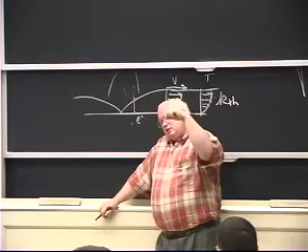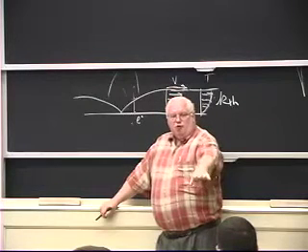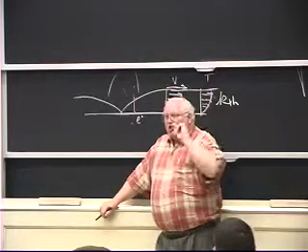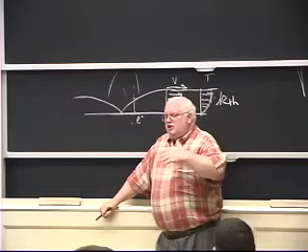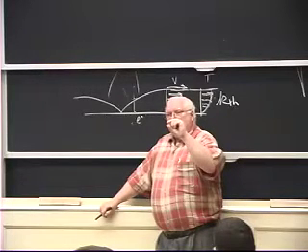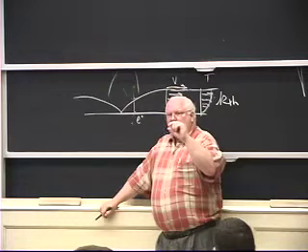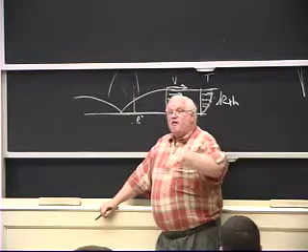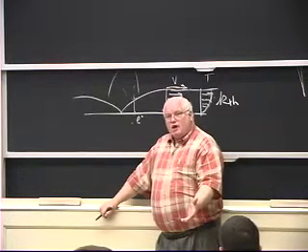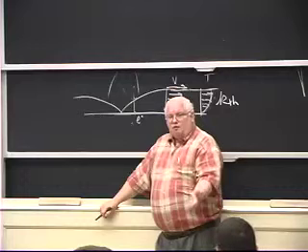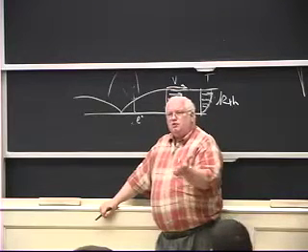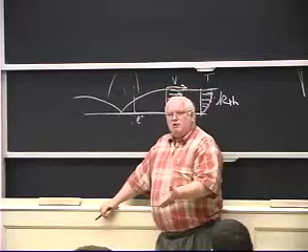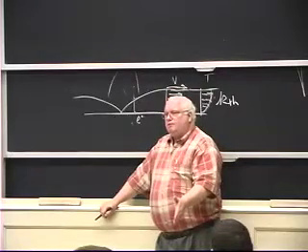And remember, I told you that I don't care about voltage. You mentioned voltage. It's current that carries the heat. And voltage, the arc will develop whatever voltage is necessary to ionize the gas. And if I have easily ionized metal vapors in that arc, I will have a much lower temperature. The arc will go down to its lowest possible temperature to generate enough electrons to carry the current that the power supply is imposing on it.